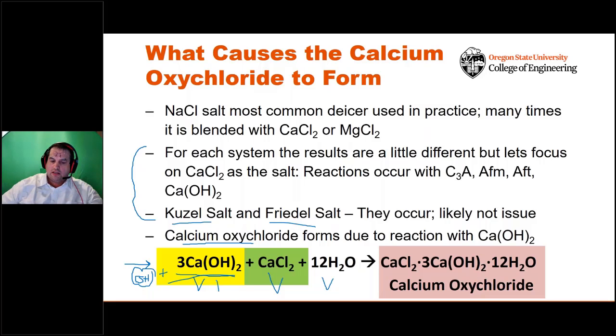Now, this calcium hydroxide actually helps us out a lot in preventing pH drop, which helps to passivate steel, for example, in the system. But this calcium hydroxide is soluble, and in the presence of calcium chloride will react to form this thing called calcium oxychloride. Now, this calcium oxychloride is problematic, not only because it's got a great big long chemical composition, but the fact that it's 303% larger than the original calcium hydroxide, right?